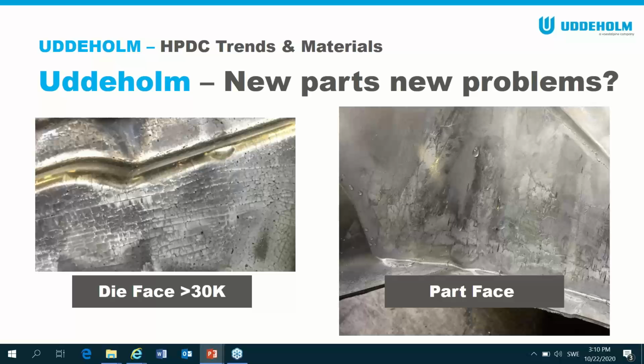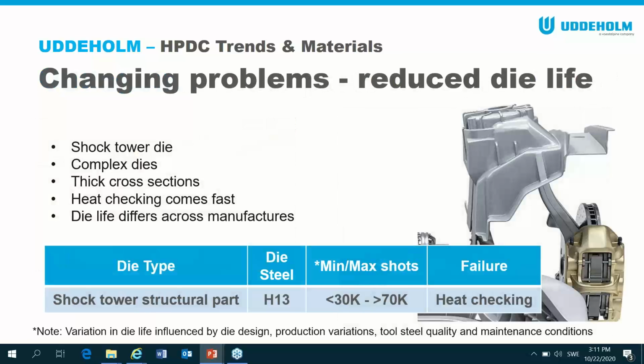And the part itself has got heavy heat check damage on it as well. And that has to be ground out, actually. So in this manufacturer, they don't actually repair the die. They actually grind the part itself. And a typical production on the longitudinal bridge for this manufacturer could be anything up to 100,000 parts. But they start having to regrind it from quite early on. So maybe you see here 30, 40,000 parts and they're having to regrind. And it's the same with shock towers as well, just different levels.